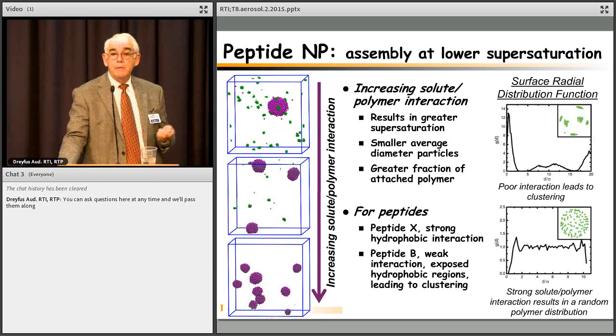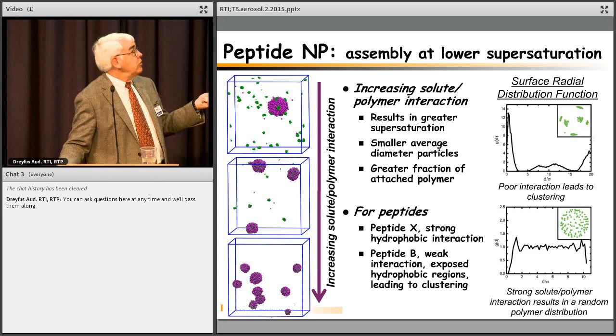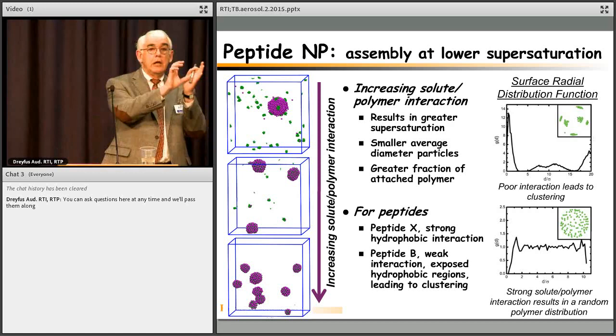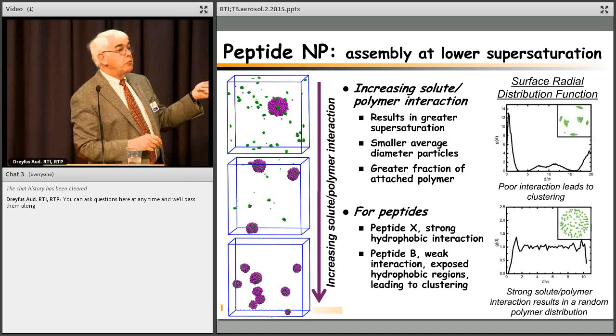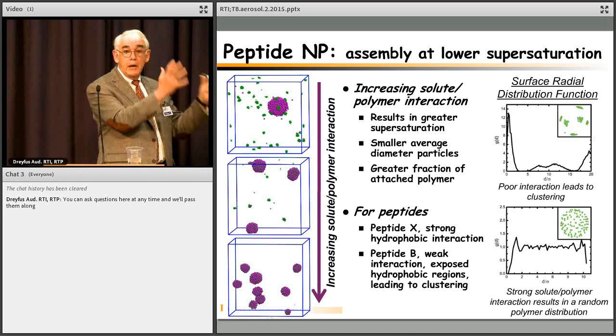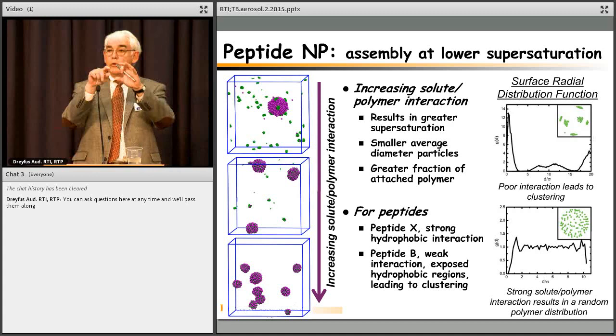However, if you decrease this energy, and have something where the energy between the hydrophobic block and the nanoparticle surface is weaker, then the block copolymer forms micelles. That is, the block copolymer hydrophobic block interaction dominates, and you form micelles. And on the surface, you form clusters. That is, these things hit on the surface and move so that the hydrophobic blocks are all in an aggregate, and you have wide spaces here which are not protected.